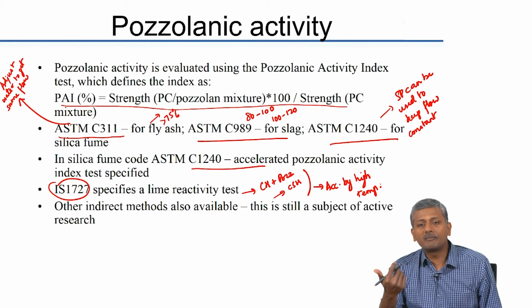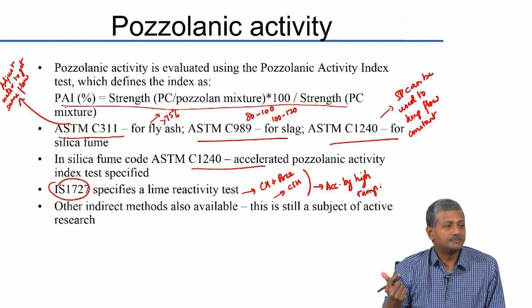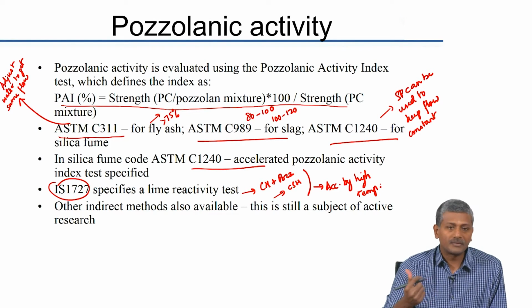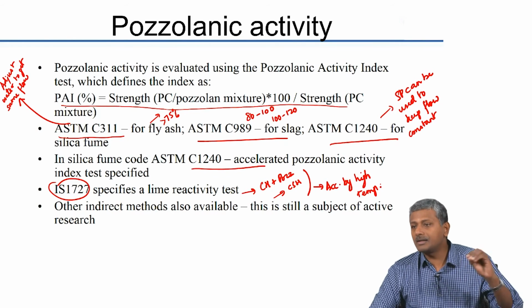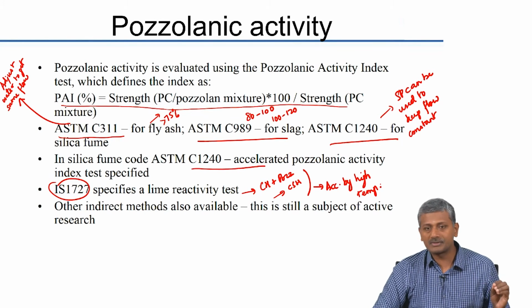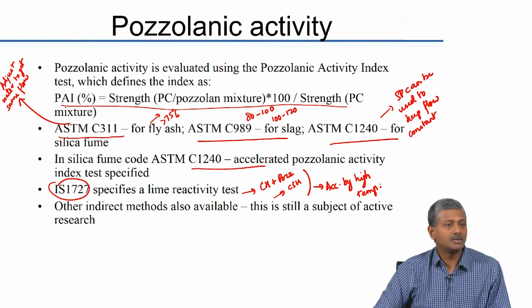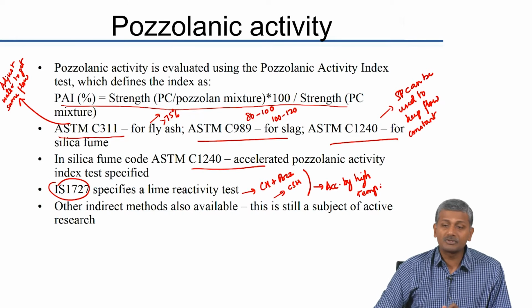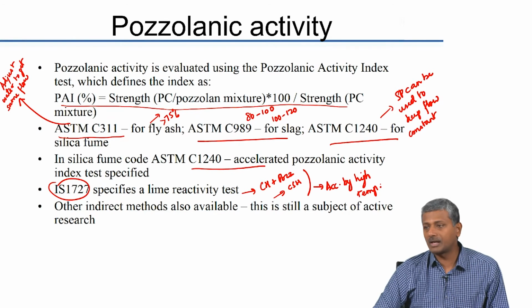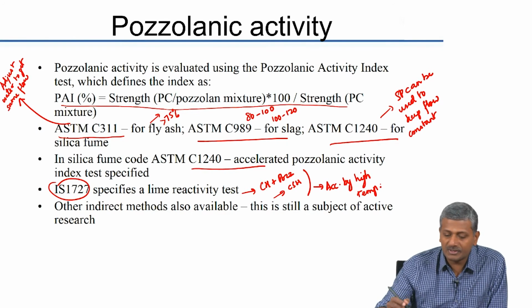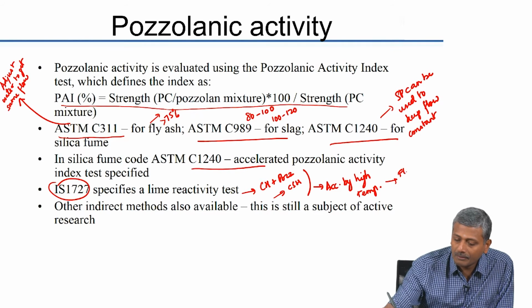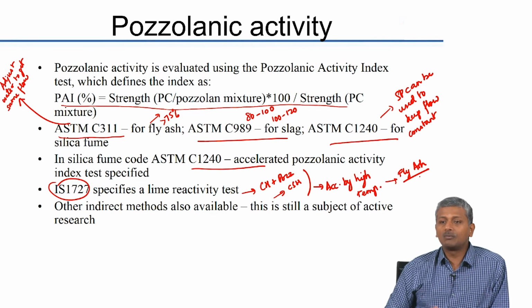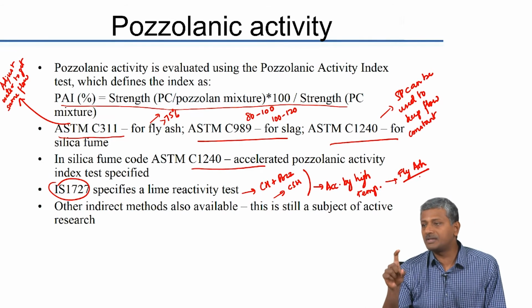Now, obviously there is a problem here, no? What is the problem? It is not reflecting the true system. In the true system, there are alkalis and there is gypsum, which are going to promote this reaction to happen faster. But in the absence of those, you do not get a perfectly good reaction in this case. Now, as per IS 1727 for fly ash, the lime reactivity test is only measuring the compressive strength of cubes prepared with these mixtures.